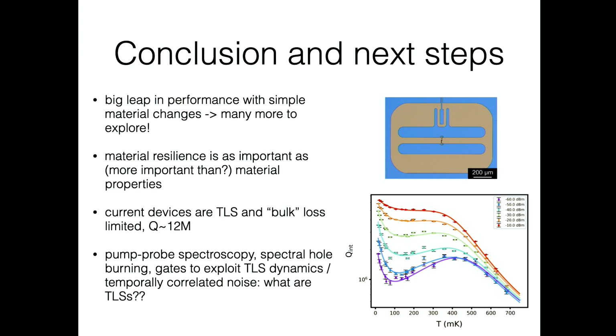The other big takeaway, and this was maybe a little bit of a surprise and also a little bit of an uncomfortable interdisciplinary thing, is that material resilience is actually as important and maybe even more important than the underlying material properties. This is a very uncomfortable space for both physicists and material scientists. I think what material scientists would usually like you to do is just say, here are all the properties that I need, deliver me a film that gives me those properties. But this is now a totally different desideratum. This is, I need a film with these properties and I'm going to dip it in acid and do terrible things to it. And I want you to leave open this big parameter space for me to be able to anneal it and stick it in plasma and do all of this other stuff. And now, this is a very different kind of design space for these materials.